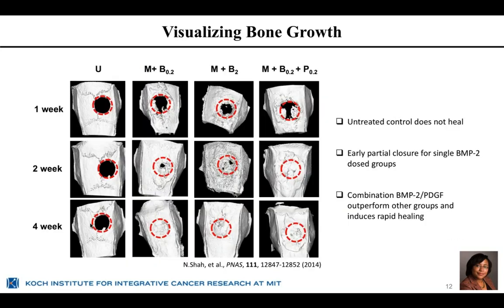And when we actually look at the results, we use a rat cranial defect model. So in this case, we generate essentially these holes in the cranium of rats at a size that is so large that it cannot heal. So this first column shows the untreated animal, and you can see that at no point do we get true bone generated in that defect. In micro CT, we can see the generation of bone in a membrane that is coated with a layer by layer film that only contains the BMP2 at 0.2 micrograms. And we see that we're getting regeneration by the 4-week point.